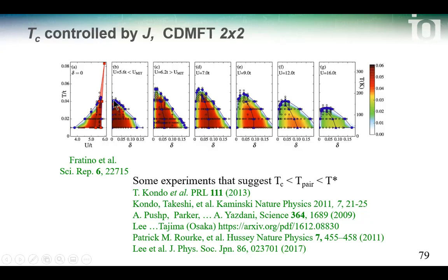If you're at weak coupling here, and you increase the hopping t, it's like decreasing U, so you go this way. Because this way, if you decrease U, the superconductivity goes down. But it's a very simple-minded picture. It's not based on actual calculations of the hopping and everything. I assume that U doesn't change with pressure.